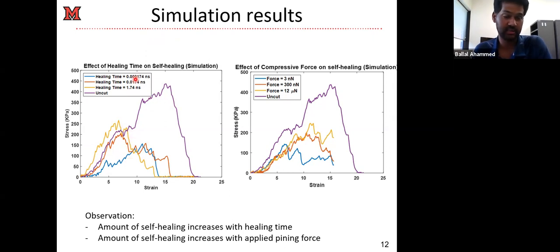But it's good that the peak stress is increasing with the healing time, which means the material is healing better. Also, if you look at the force, we see that when we apply more force, from 3 nanonewton to 300 nanonewton to 12 micronewton, the material is behaving better. It's recovering its properties well with time. So why is that happening? Our experimental colleagues cannot see the atomistic details, but we can, and we can understand the origin of the self-healing behavior atomistically, which we would like to explore in the next couple of slides.